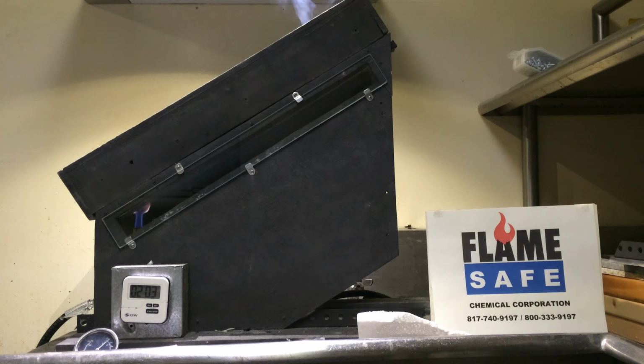Results obtained by this test method are not always indicative of the test method E84. And the accuracy of this test is usually within the parameters of approximately 95%. That's based on bias, that is the thickness of the coating that might be applied, the type of substrate that may be influenced according to the fire, in addition to other methods.